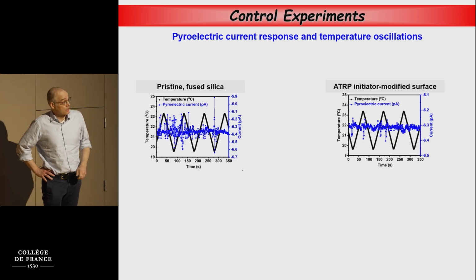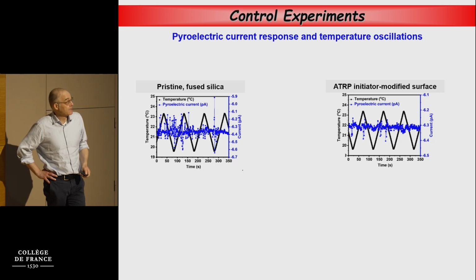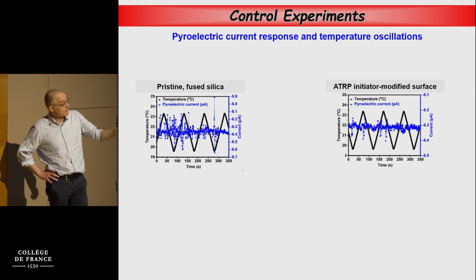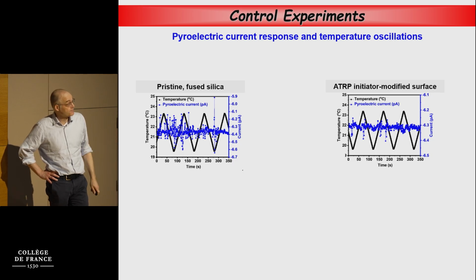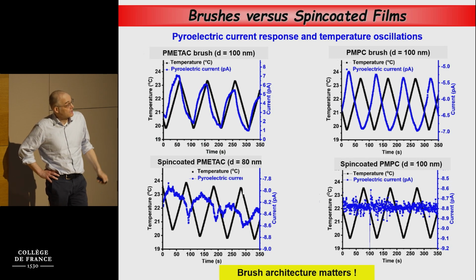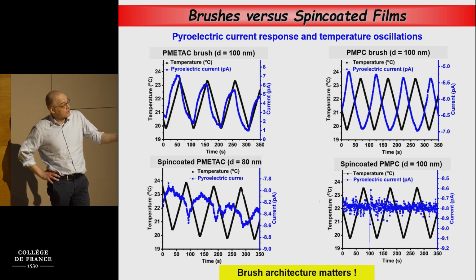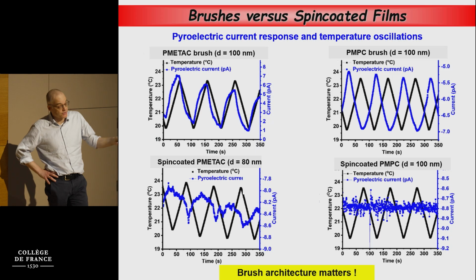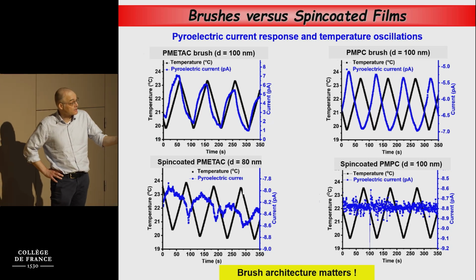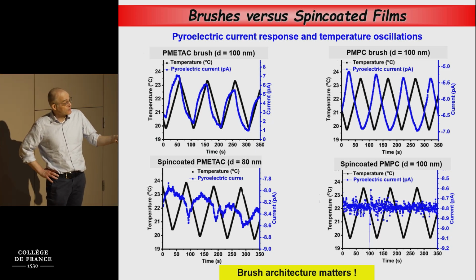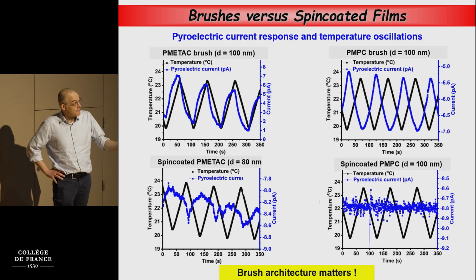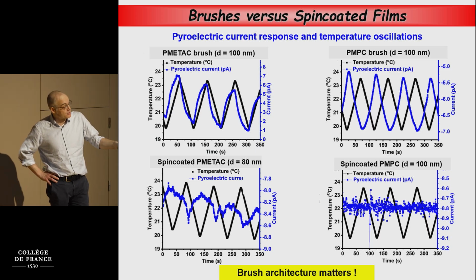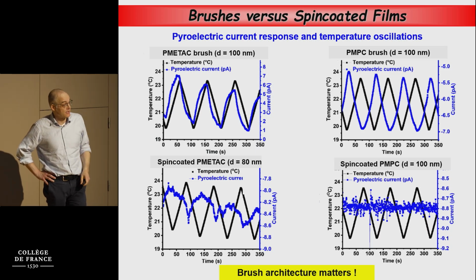Then we did a number of control experiments to try to understand what's behind this. If you do the experiment for the unmodified silica surface, there is no current. If you take the surface modified with the ATRP initiator, no current. And interestingly enough, if you take the corresponding spin-coated polymer film, so if you don't grow METAC, the electrolyte, from the surface, but make it in solution and spin cast this film, you see a very weak to no significant pyroelectric current. And if you take the zwitterion, PMPC, and spin-coat it, there is also no pyroelectric current.